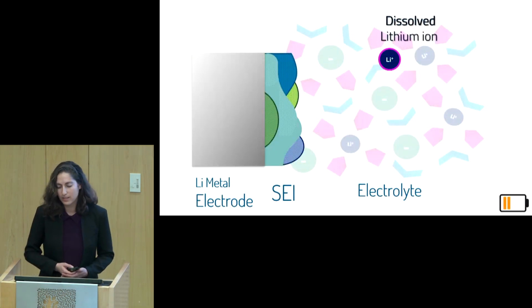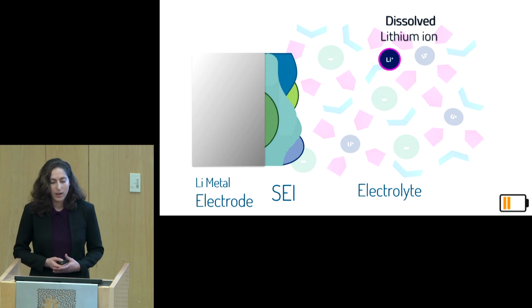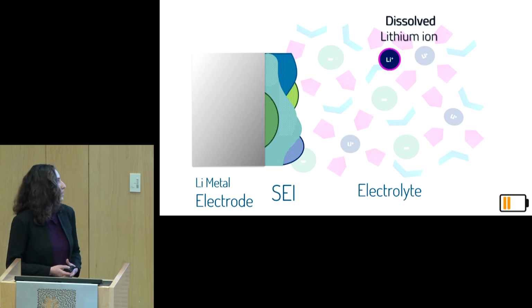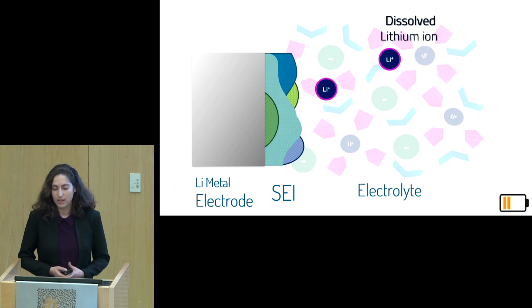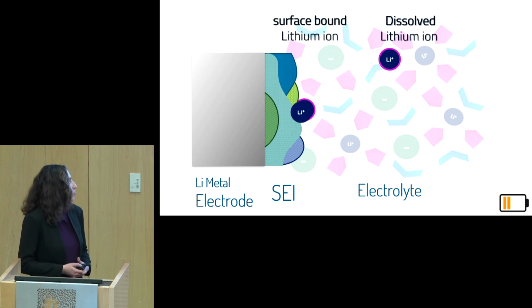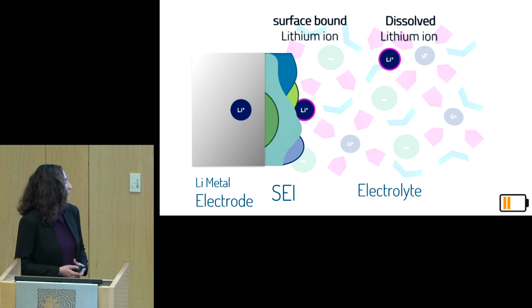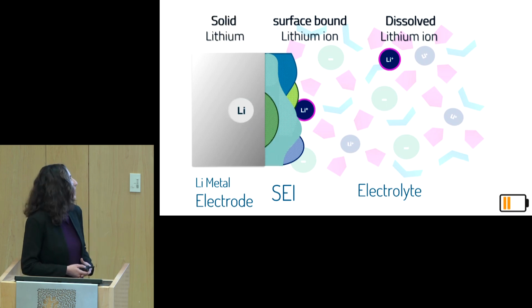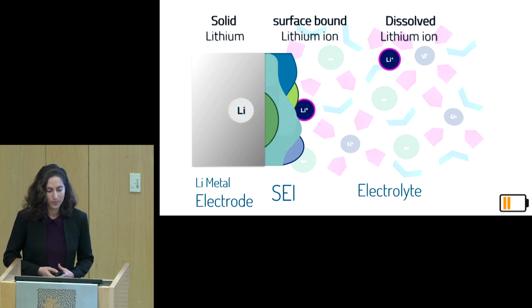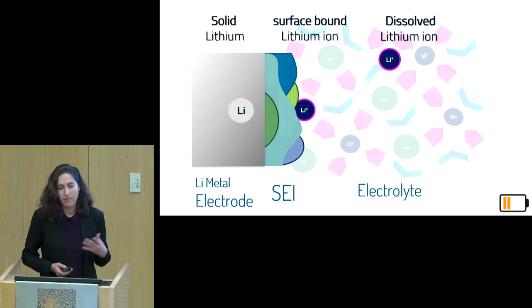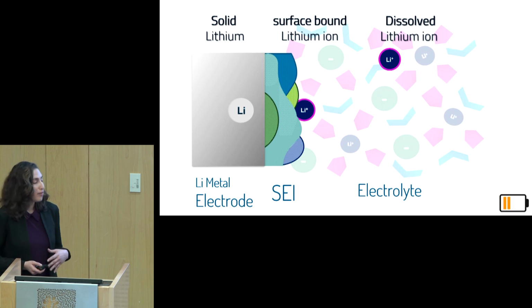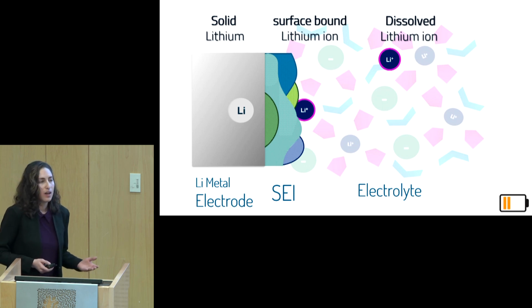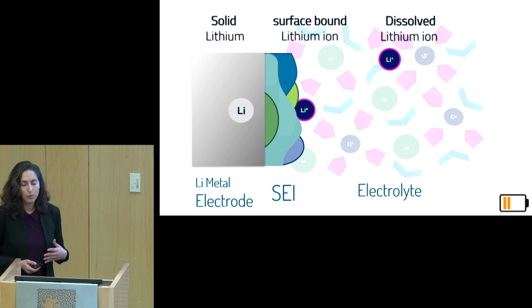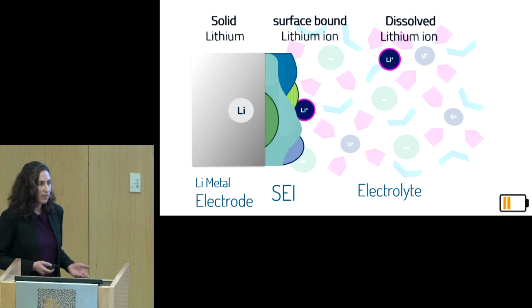Taking a closer look inside the battery, we can see the lithium ion in three distinct environments: the dissolved lithium ion in the solution, the lithium ion that is bound to the surface layer, and the solid lithium inside the electrode. In different batteries, which have different conditions and different electrolytes, different surface layers will form. Some of these surface layers are beneficial to the battery. They allow the lithium ions to pass through into the electrode while protecting the electrode from degradation.